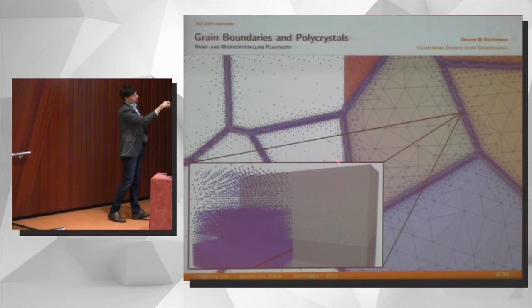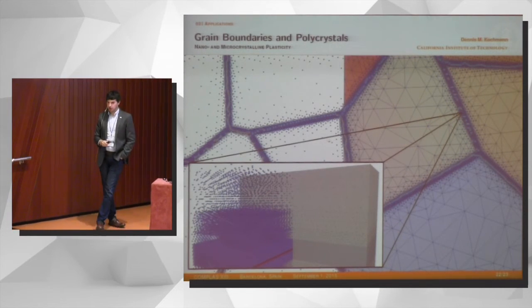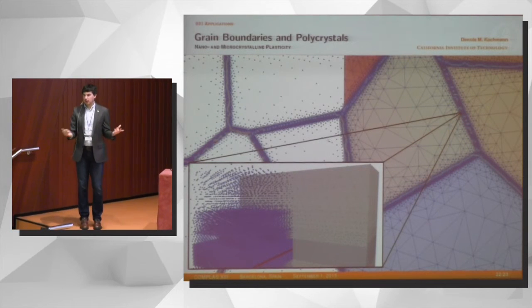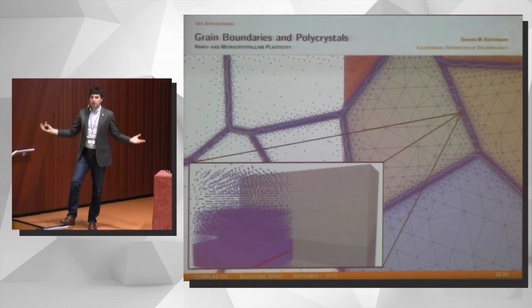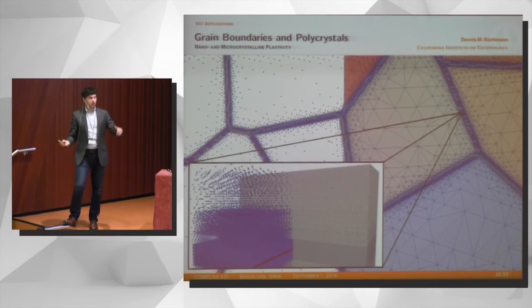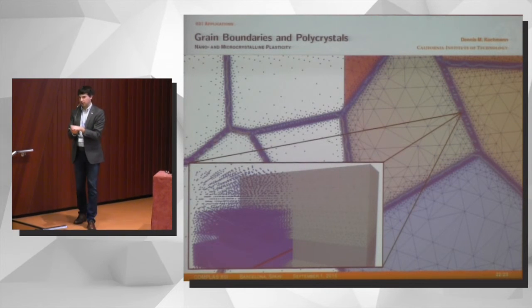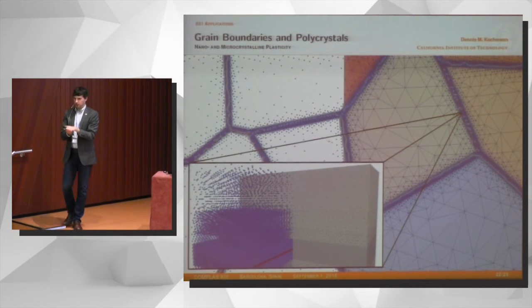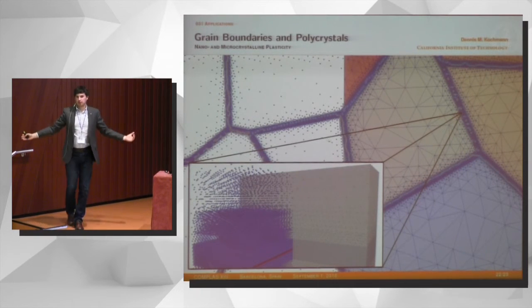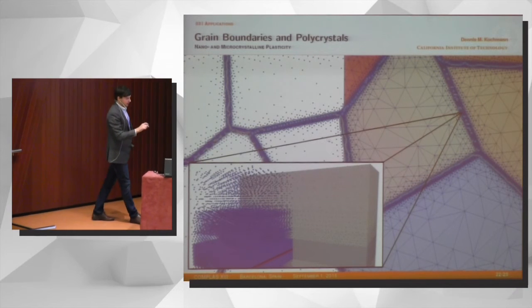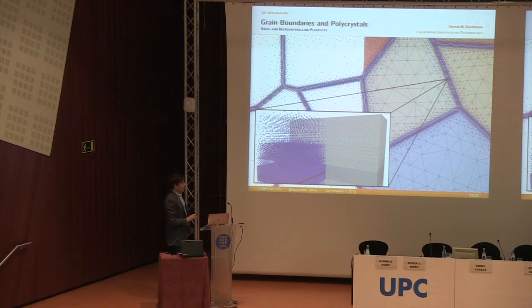We are readily coarsened up here, so it's much more efficient than running this with atomistics. And that allows us to do, in principle, arbitrary grain boundary misorientations. Of course, this is easily done for coincidence site lattices, but if you have a very complex grain boundary that requires you to have a huge unit cell, this can easily and efficiently be done in this context. And so,